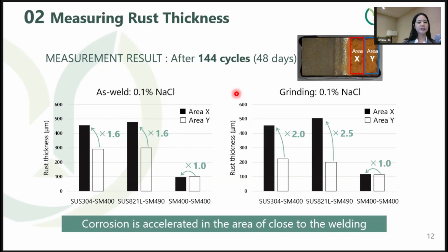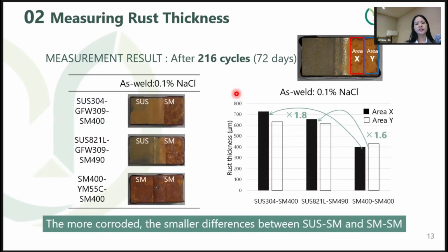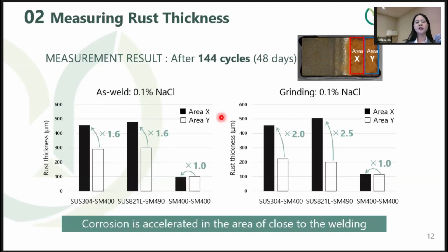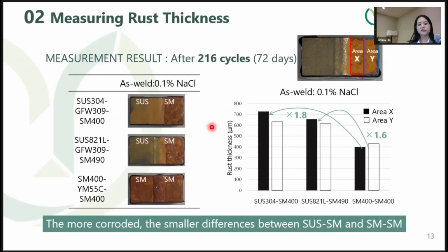From this one, the corrosion is accelerated in the area close to the welding, which means the shorter distance is more accelerated. And this one shows the 216 cycles, which means a more accelerated one. As shown in the right figures, it is of course more accelerated than before, but the more corroded, the smaller the differences between SUS-SM and SM-SM. It might be that the SM-SM also corrodes more and more.